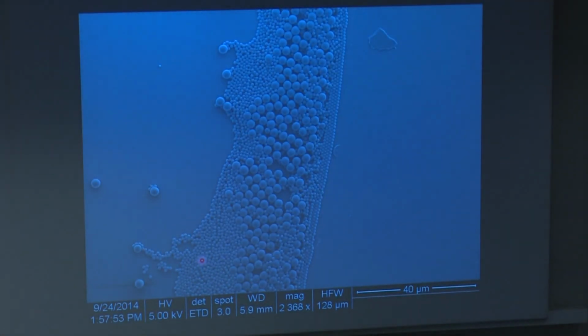That's just another static example. So you can have a situation that if the concentration is slightly high, you can get a layer of small particles because as the big particles form, the small particles can go around the big particles to reach the contact line, close to the contact line. The big particles are stuck at some distance away from the contact line. And then later on, once the concentrated big particles get large enough, so the small particles can't filter through the pore spaces, you can get another layer of very small particles.